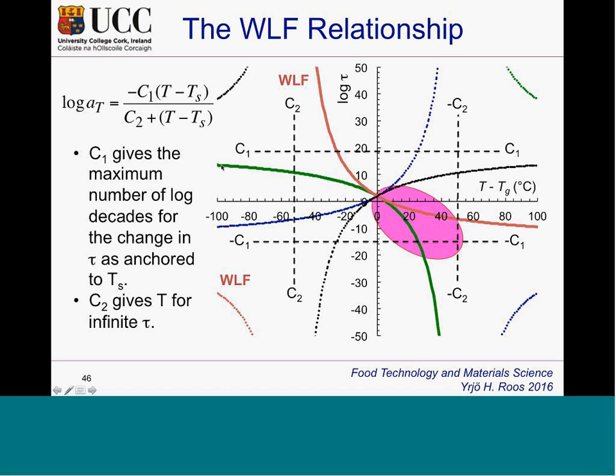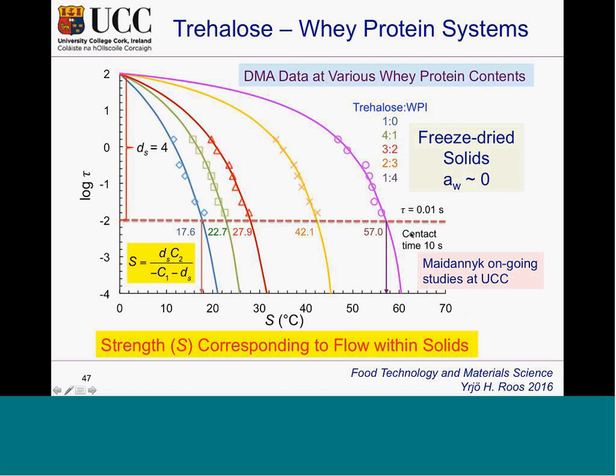In fact, in some of the dynamic mechanical analysis data we have done for a mixture of trehalose and WPI, we see that it softens nicely above that. With water concentration, we have different T minus Tg. Now we have taken the relaxation time decaying from 100 seconds to 0.01 seconds, which is the point where stickiness occurs in spray drying or other relevant flow. I can show that if we take that as a strength parameter, then depending on the composition, we can measure what the strength is.